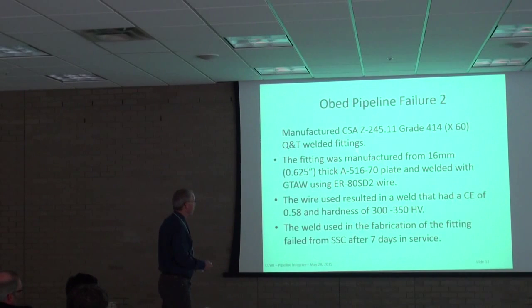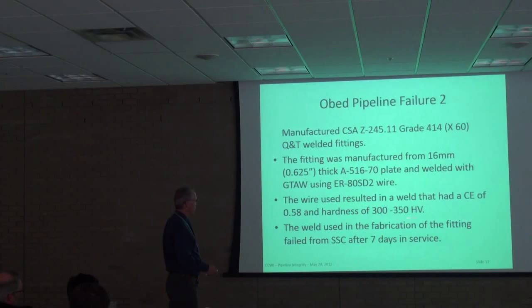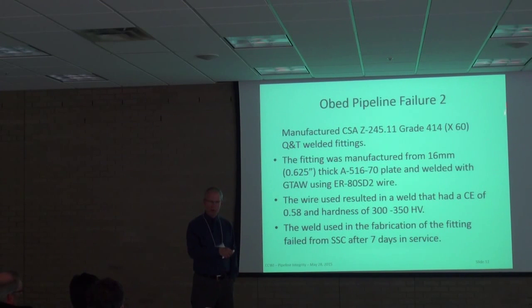So just a couple of things when I talked about these, the standard number in sour service is about 248. So you want to be below 248 Vickers. And so almost everything in sour service, all your weld procedures, everything's designed to be down below that number. So once you start getting up into the 300s, you're into that zone where your residual stresses are so high that it makes you very susceptible to sulfide stress cracking.